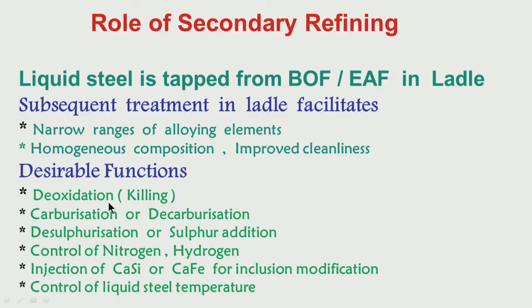So what are the desirable functions? I have talked about first deoxidation, which is known as killing. This is the first requirement for any secondary refining process, and it is the primary requirement for getting a clean steel. Next is decarburization, or in one or two cases even carburization. That means control of carbon in the bath. Then desulfurization, or sulfur addition in maybe one case only, when you need more sulfur for good machinability. Otherwise, in most of the applications, we require less sulfur. So desulfurization is one important requirement.